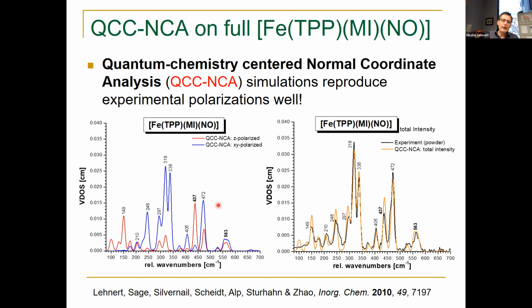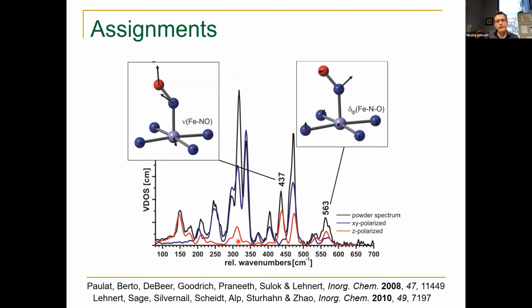And I don't want to dwell on this too much, but you can see that we're able to reproduce the fact that this 437 wave number feature is fully out-of-plane polarized, and then we're able to reproduce the mixed polarization of that mode at 563 wave numbers, right? And to make a long story short, we can then assign them. So the 437 mode is the iron NO stretching mode, and then the 563 is the dominant bending mode, but has some stretching character as well, which is the reason why we have the mixed polarizations.